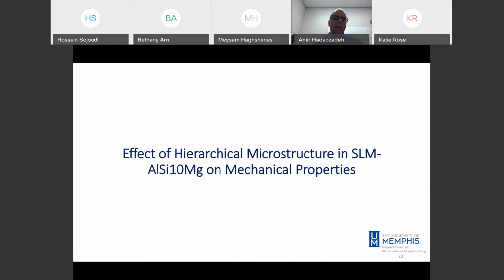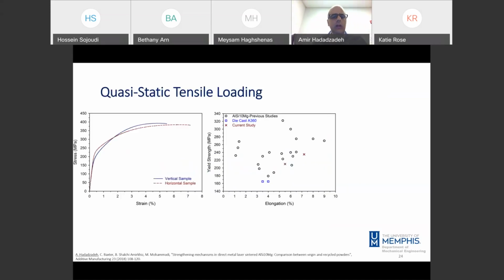So far we explored that, but the big question is, does this microstructure affect or control the mechanical properties? And obviously the answer is yes. So we did quasi-static tensile tests on those samples, vertical and horizontal samples, and we see the results here. And we compared the results to a die-cast counterpart. The same material fabricated through die-cast.